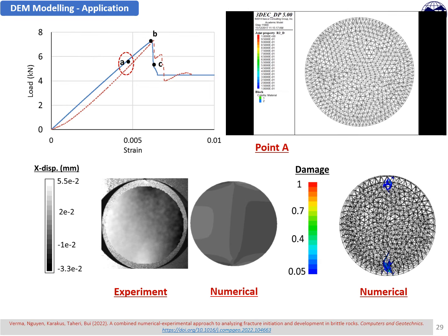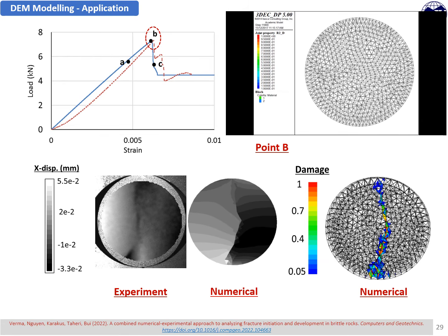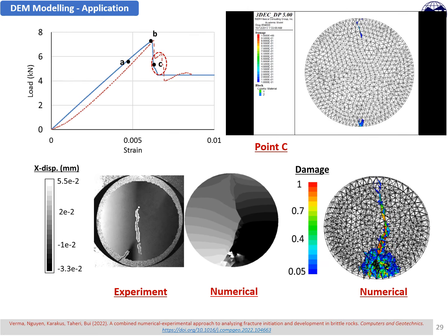From experimentation we obtain these strain contours using the digital image correlation technique, whereas from numerical modeling we got the strain contours straight away. At stage 2, the disc specimen cracks instantly, in a fraction of a second, and that cracking pattern from the numerical modeling also aligns well with the experimental observations, as you can see in the slide below. And in stage 3 post-peak behavior, we can see a significant amount of secondary cracks at the loading ends, which also correlates well between the numerical output and the experimental observations. The video shows the damage evolution across the specimen diametrical axis in this conventional approach.